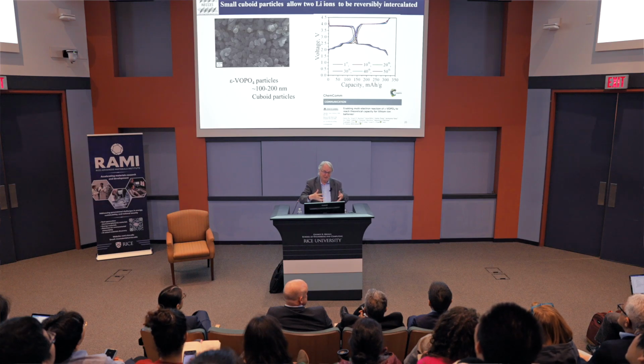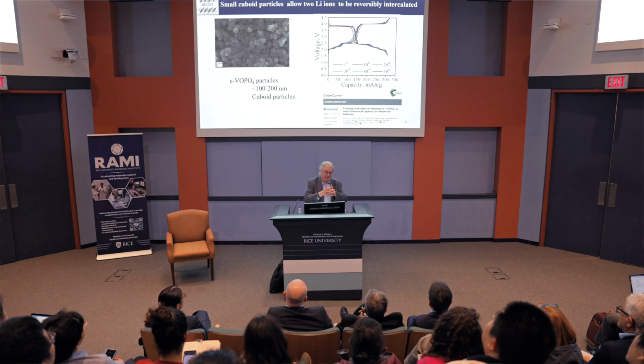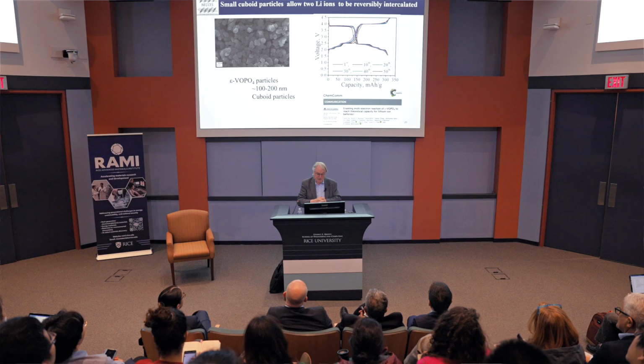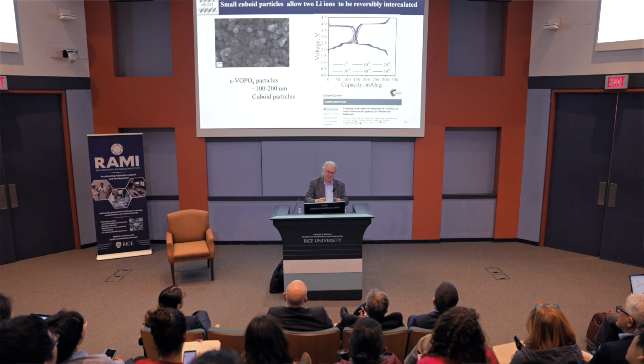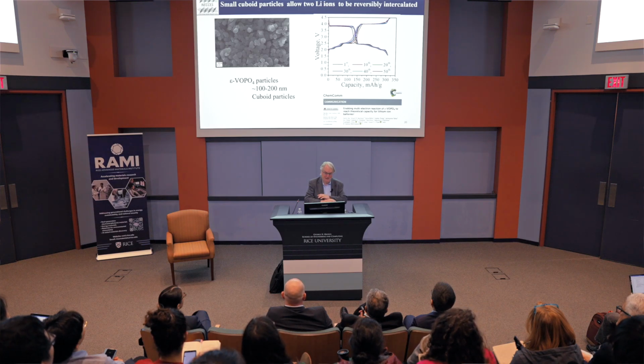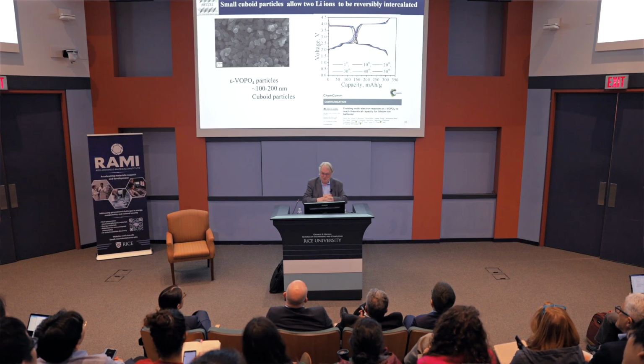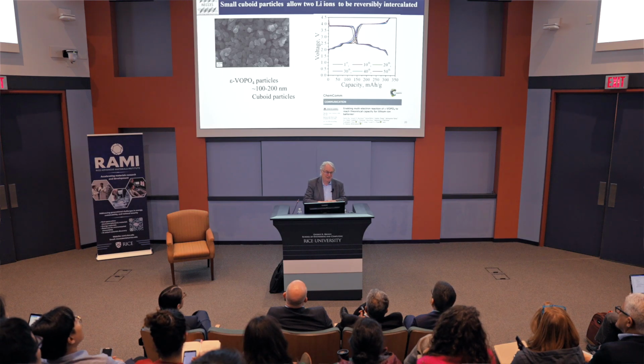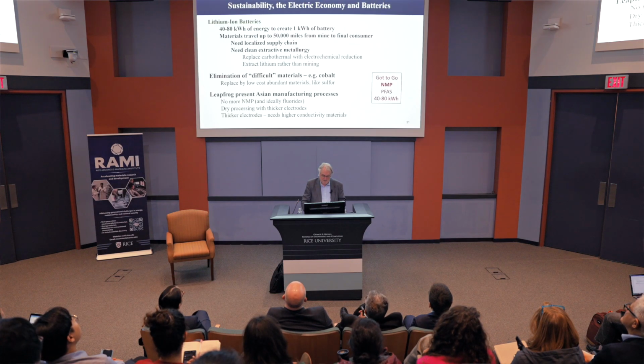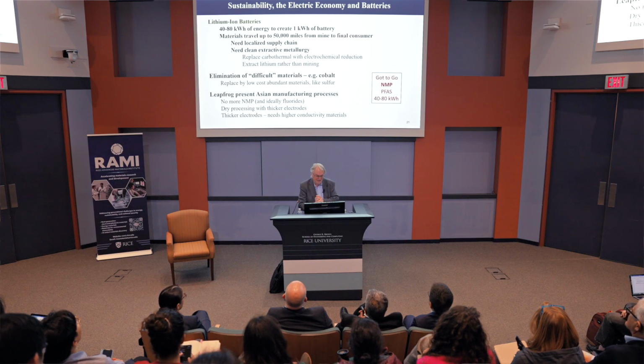You can stuff 2 ions into a lattice with that lattice not being destroyed. So we've worked on this a lot. We have challenges making it in large quantities, and we have challenges of it wanting to react with the solvents in the electrolyte. The material itself is perfect. It's just as good after a few hundred cycles as at the beginning. And now several companies are working at commercializing this material. So let me get off the technical stuff and get into some of the other issues.